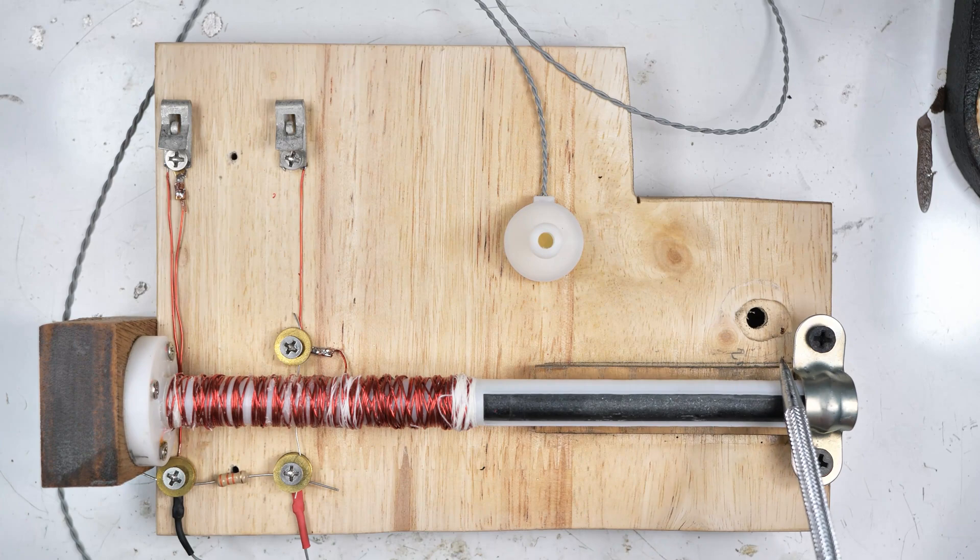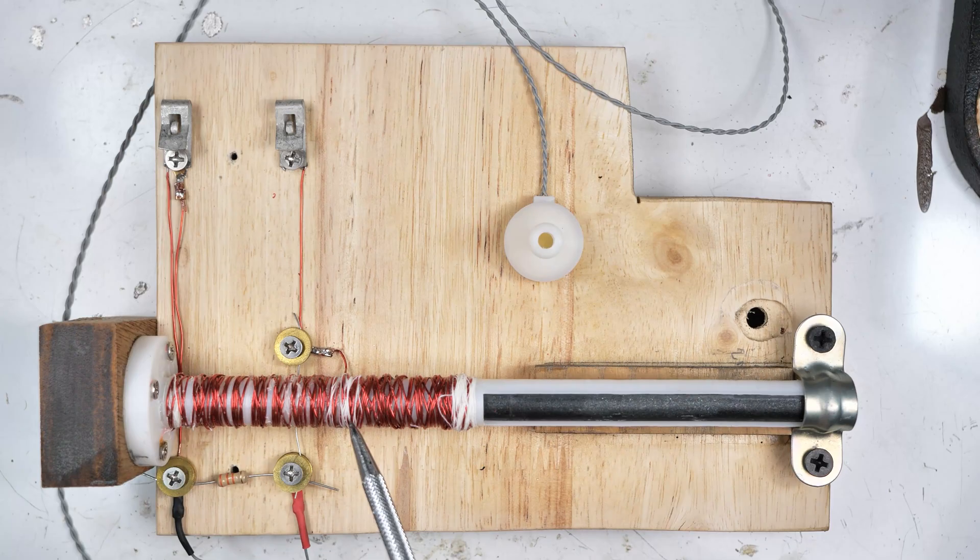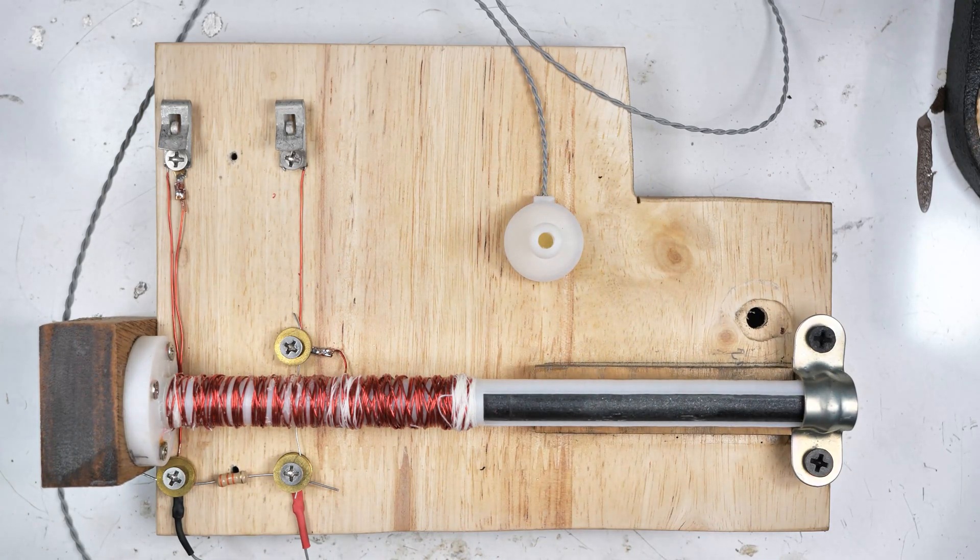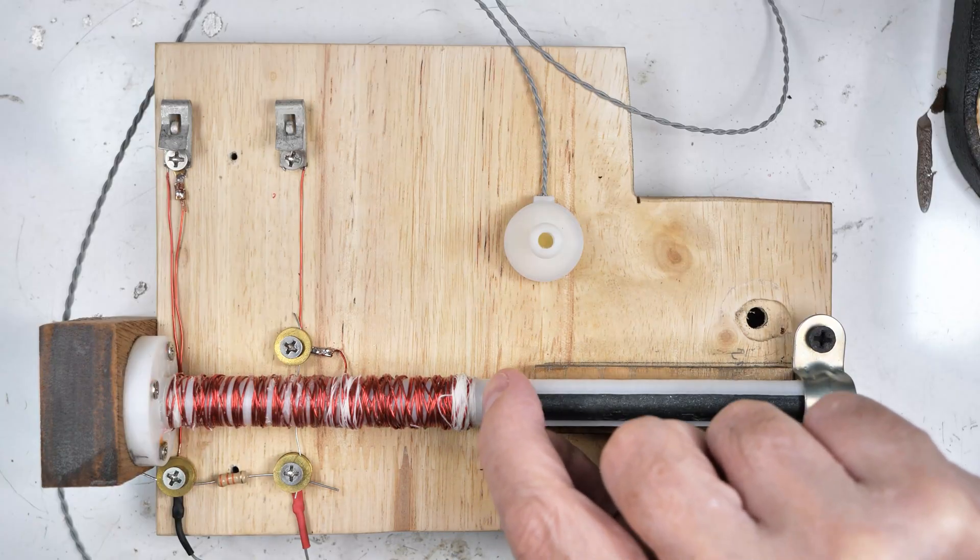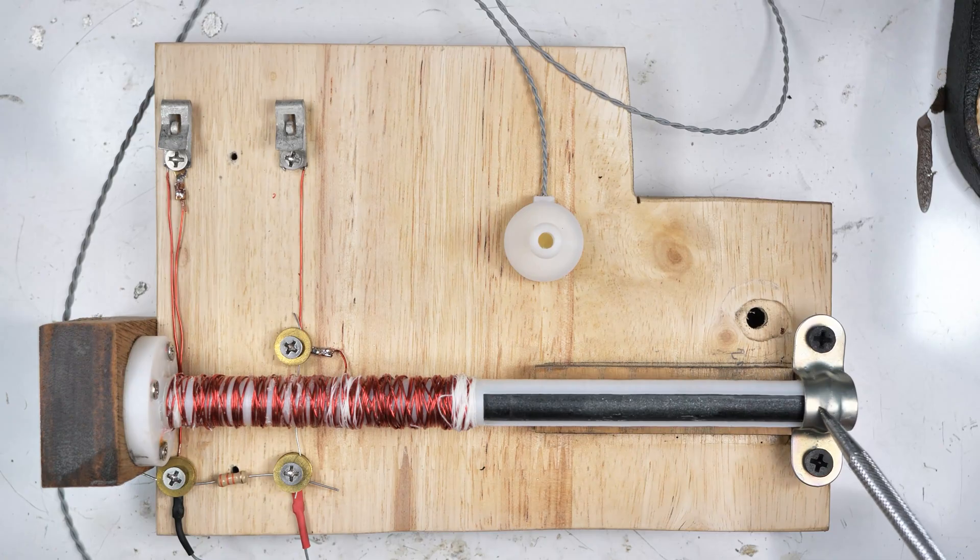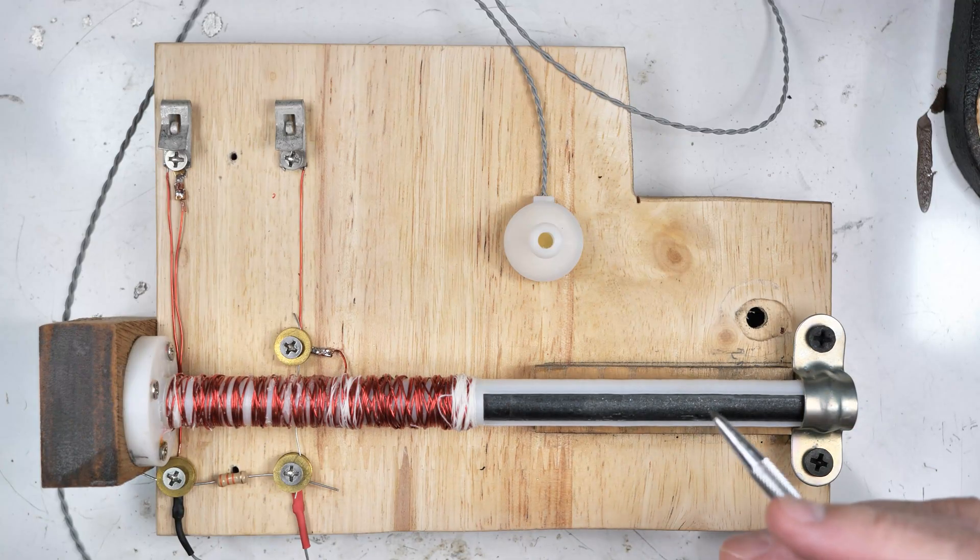This is a 3D printed tube. If I had to do it again, and I may do it again, I would make it PVC tubing or acrylic because it's tougher. However, the 3D print has grain in it like wood. And like wood, it will break easily along the grain. The grain stands in here like this, and it will break very easily. I tested it. It will snap there pretty easily. So that's one of the reasons I put in this thing, so it doesn't get lifted up or whatever by this. And some strength. It will add some strength.